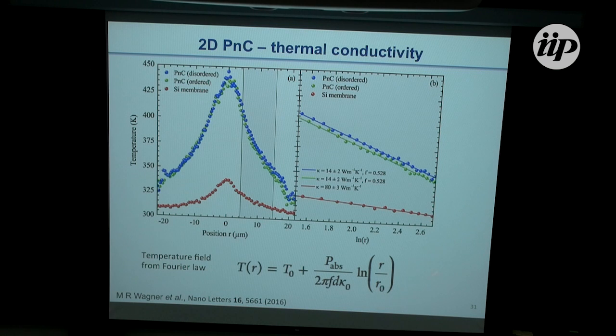It was quite an involved calculation considering all the scattering from this type of holey structures, with disorder and without disorder, etc. Nevertheless, it was possible for us to establish, without any doubt, that positional disorder hardly plays a role in the thermal conductivity at room temperature in these structures. Okay?